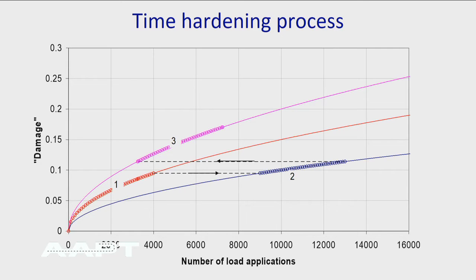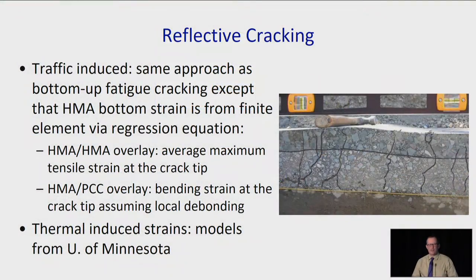We're accounting for whether we want to call it thixotropy or healing through our rest period function, which is an adjustment on our shift factor for the damage to the cracking parameter. I'm sorry, on the damage parameter. Time hardening, by the way, has been around. Carl Monismith suggested that from research that was done with Pell and so on back in the 60s.